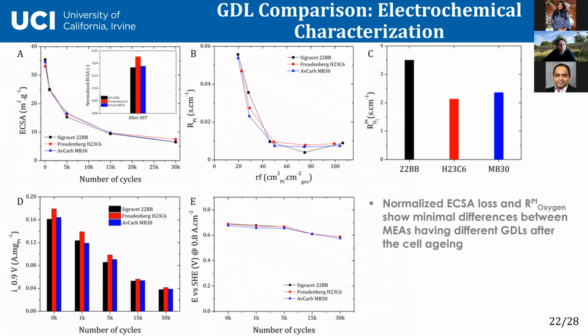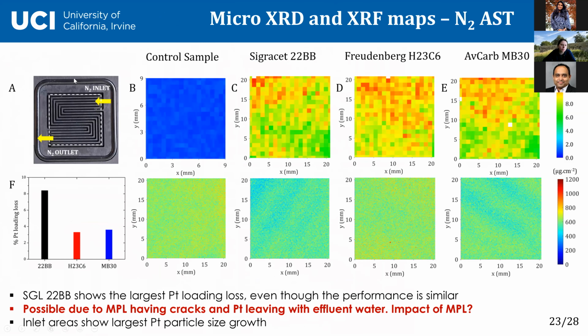We found something interesting actually. The flow field we used was this 5 cm². This is micro XRD plots of the entire area. So you can see particle size growth mostly at the inlet. We think that's somehow correlated to water production, something about hidden water management. We don't understand it quite well.